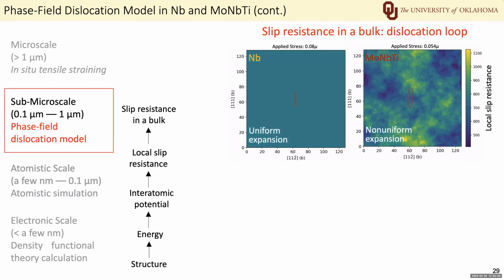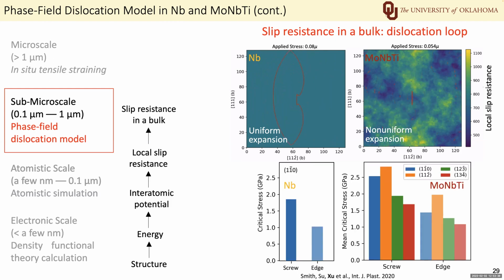So we then use the phase field dislocation model to calculate the slip resistances of a dislocation loop in both pure niobium and molybdenum niobium titanium. First we see that the dislocation loop expands uniformly in niobium, but not in molybdenum niobium titanium. We also find that similar to the dislocation line, the slip resistances of the dislocation loop on higher order planes are also lower than that on the low order 110 plane.